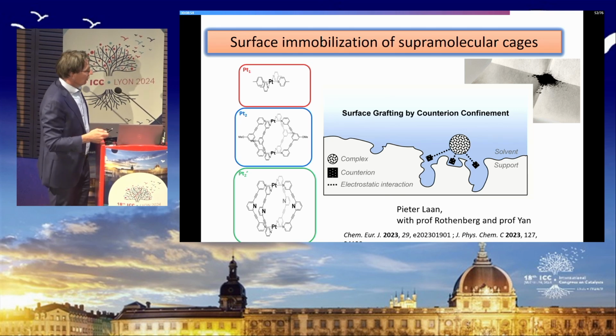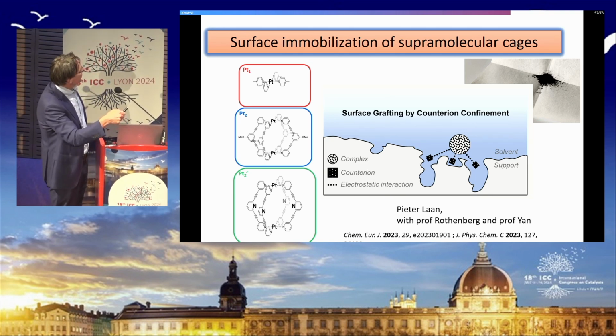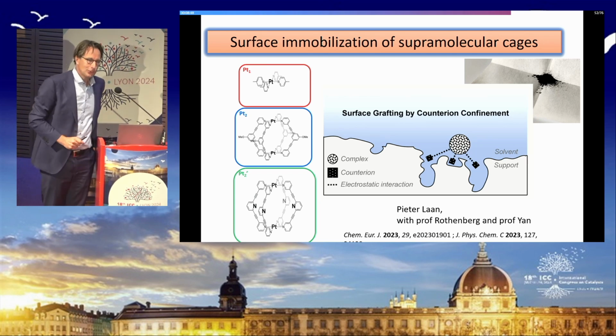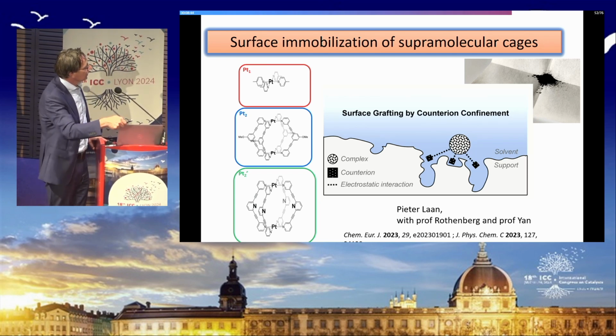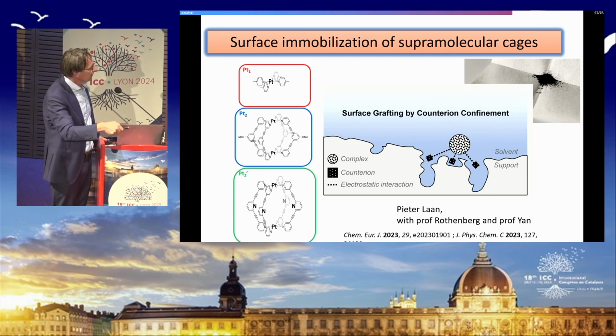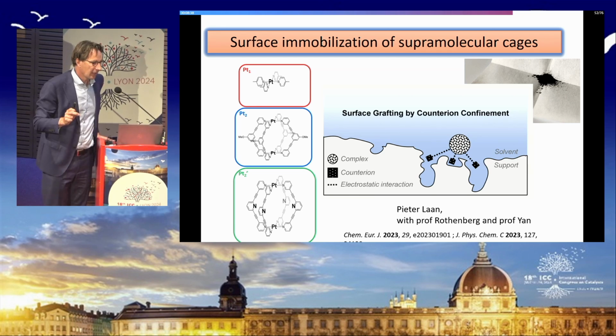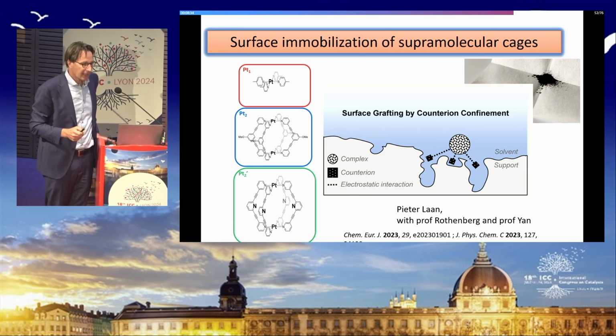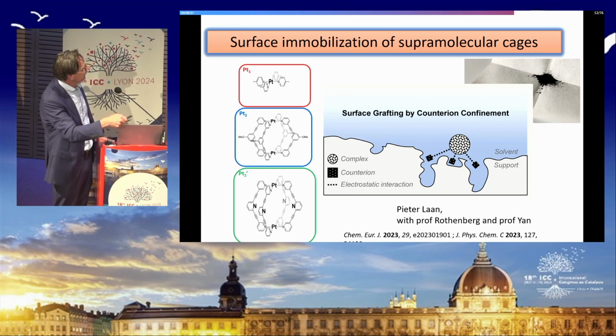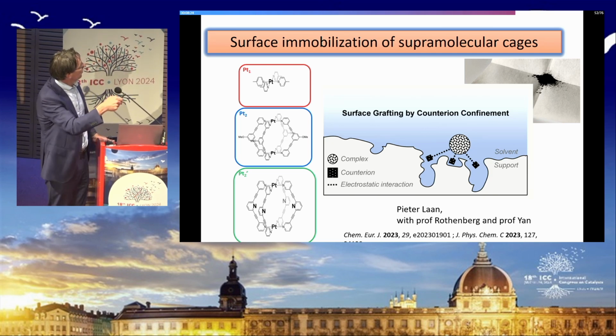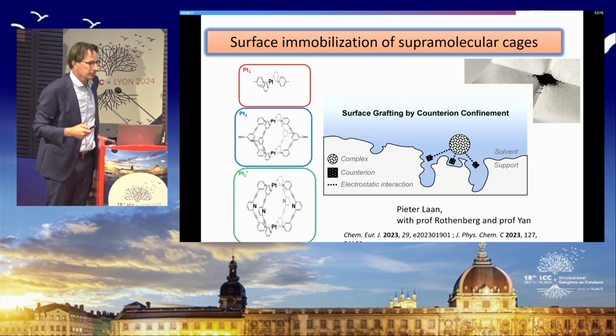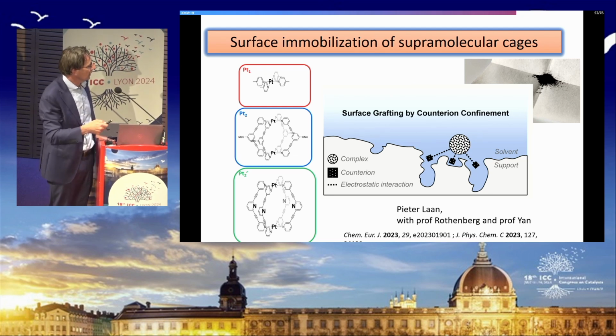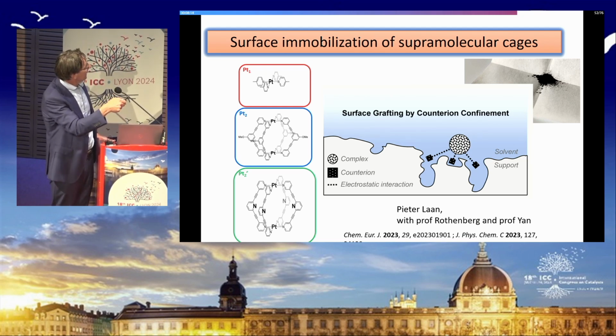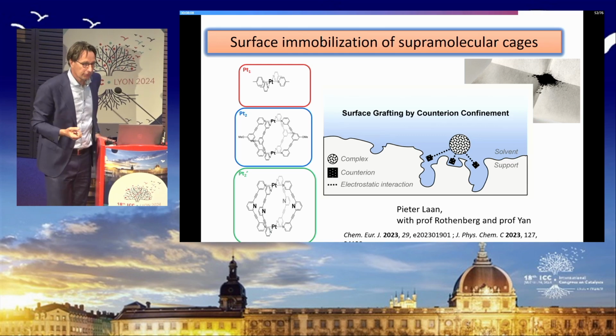Okay. So now you are introduced into these type of molecular cages that we can make. And I promised again to bridge the gap between homogeneous and heterogeneous. So with Pieter Laan, PhD student and with Professor Yan and Rothenberg, we teamed up, and they are experts in heterogeneous catalysis, and they had a material called Vulcan, which is a carbon material that is porous. And in these pores you can bind anions. And these complexes, they are cationic and have anionic BF4 minus counterions that are bound in here. So by just adding these type of complexes, we can surface graft our cages on these Vulcan type supports.